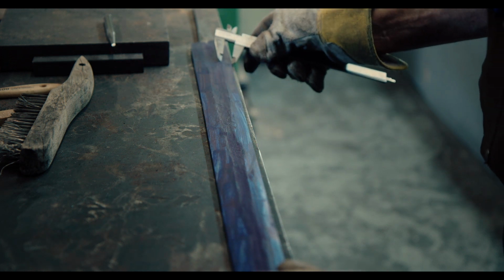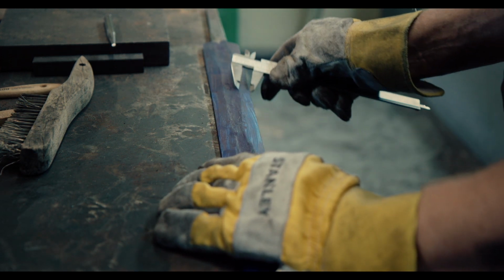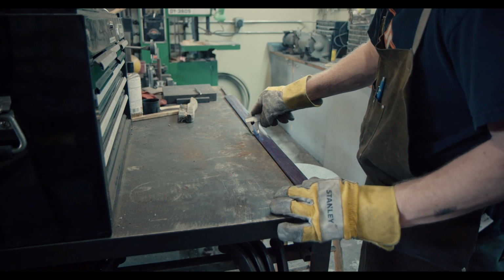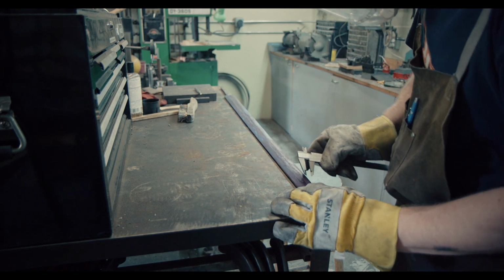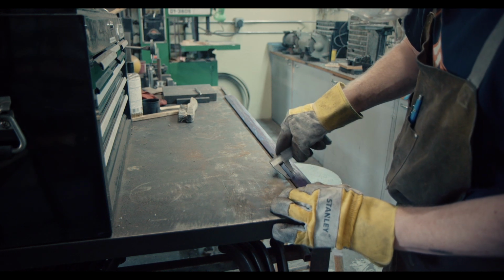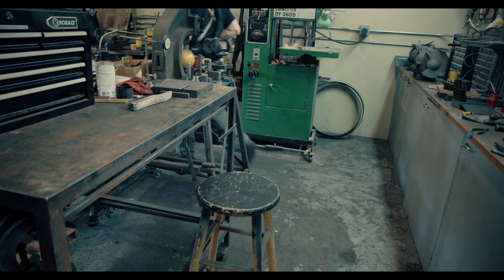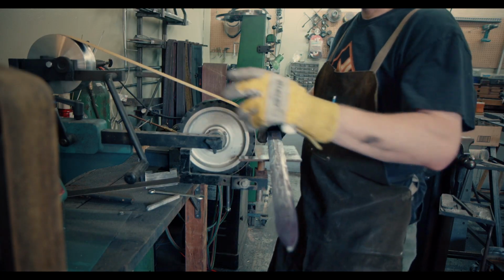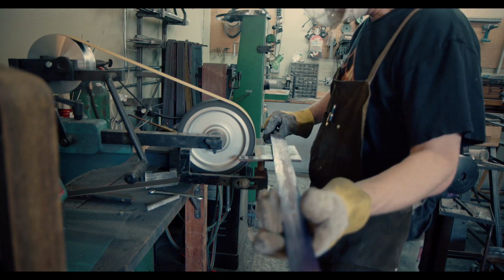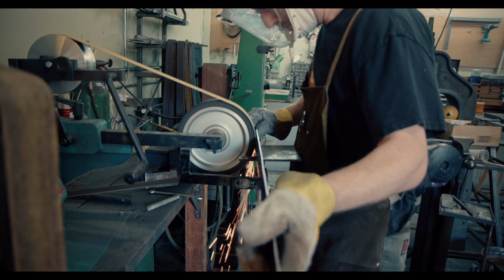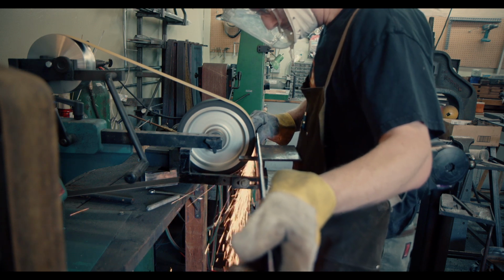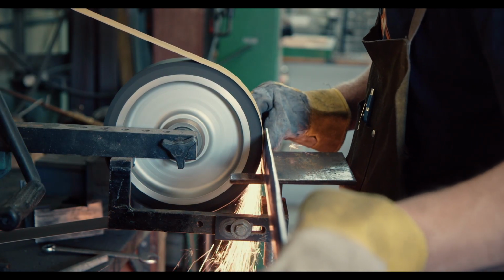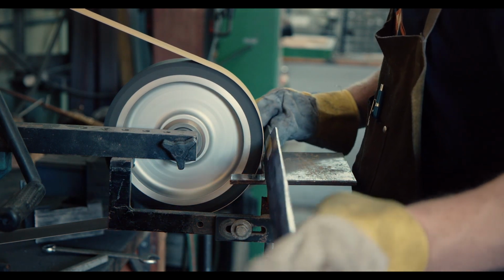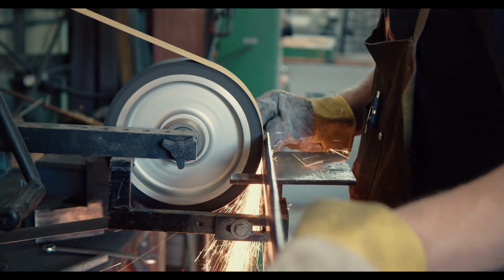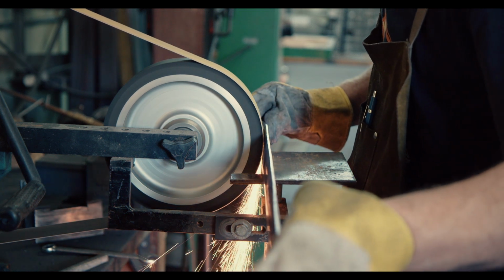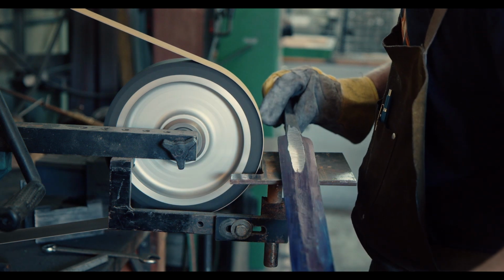Scratching the line can be done very lightly by just removing the layout fluid and does not require actually marking the steel. As with the other side, I initially take very light passes on the grinder. This gives me a feel for the positioning of the blade to the grinding wheel and sets me up for more aggressive grinding later. As you may remember, this sword has quite complex pattern welding and has the additional challenge that I need to keep the layer transition in the middle of the blade, which of course is something that I cannot see.